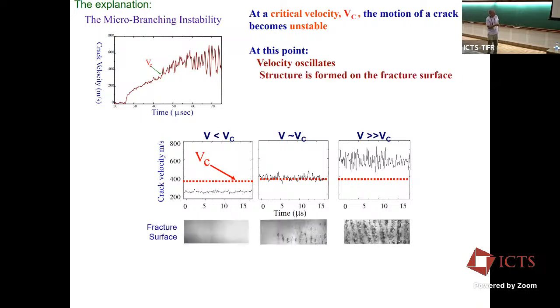at higher speeds. Now, if we look at the fracture surface, okay, now what's the fracture surface? This is our two-dimensional experiment, but it's not really two-dimensional. It has the third dimension. So we look at the surface that the crack has created, and that's what we're seeing here. It's basically featureless below this critical velocity. And all of a sudden, at the critical velocity, you start to see structure appearing on the cracked surface. These little dots are not dirt, they're real things. And as we push the velocities faster and faster, the structure becomes more and more apparent and larger.